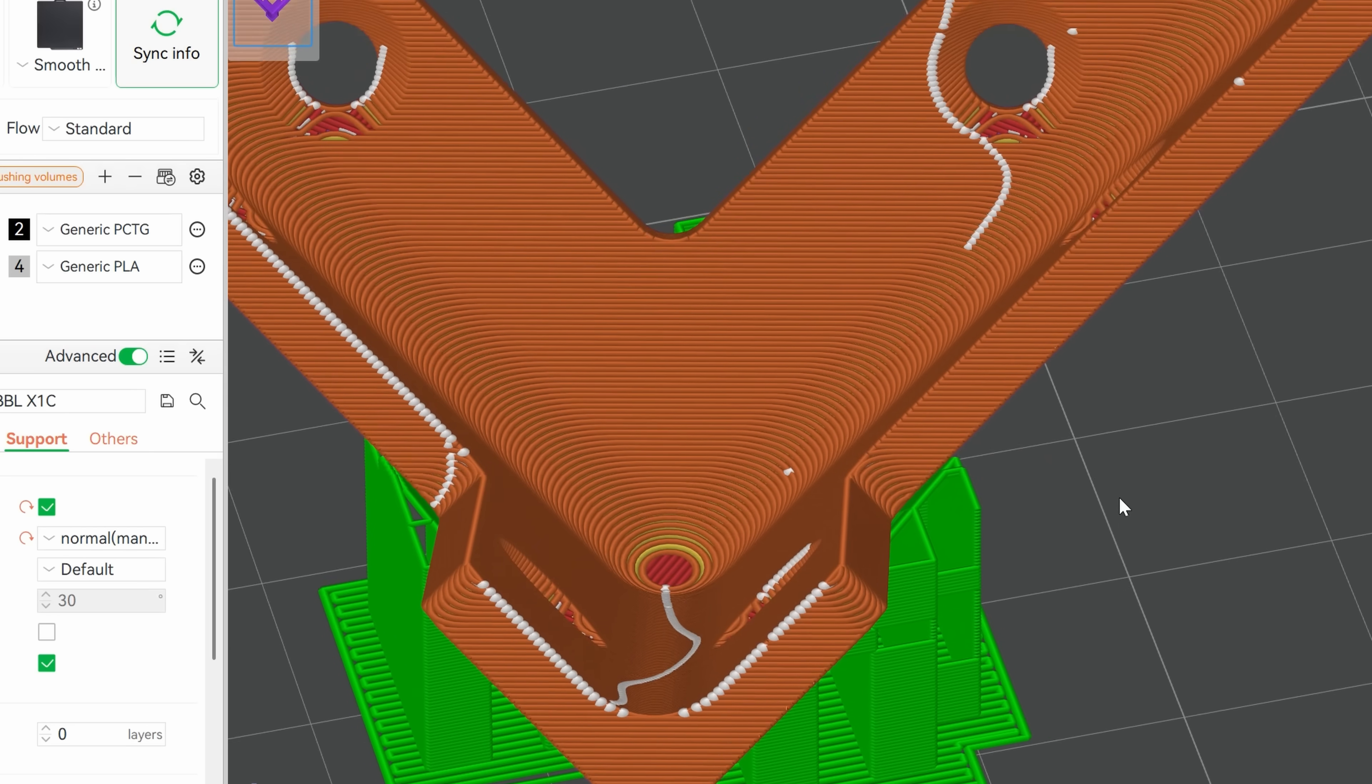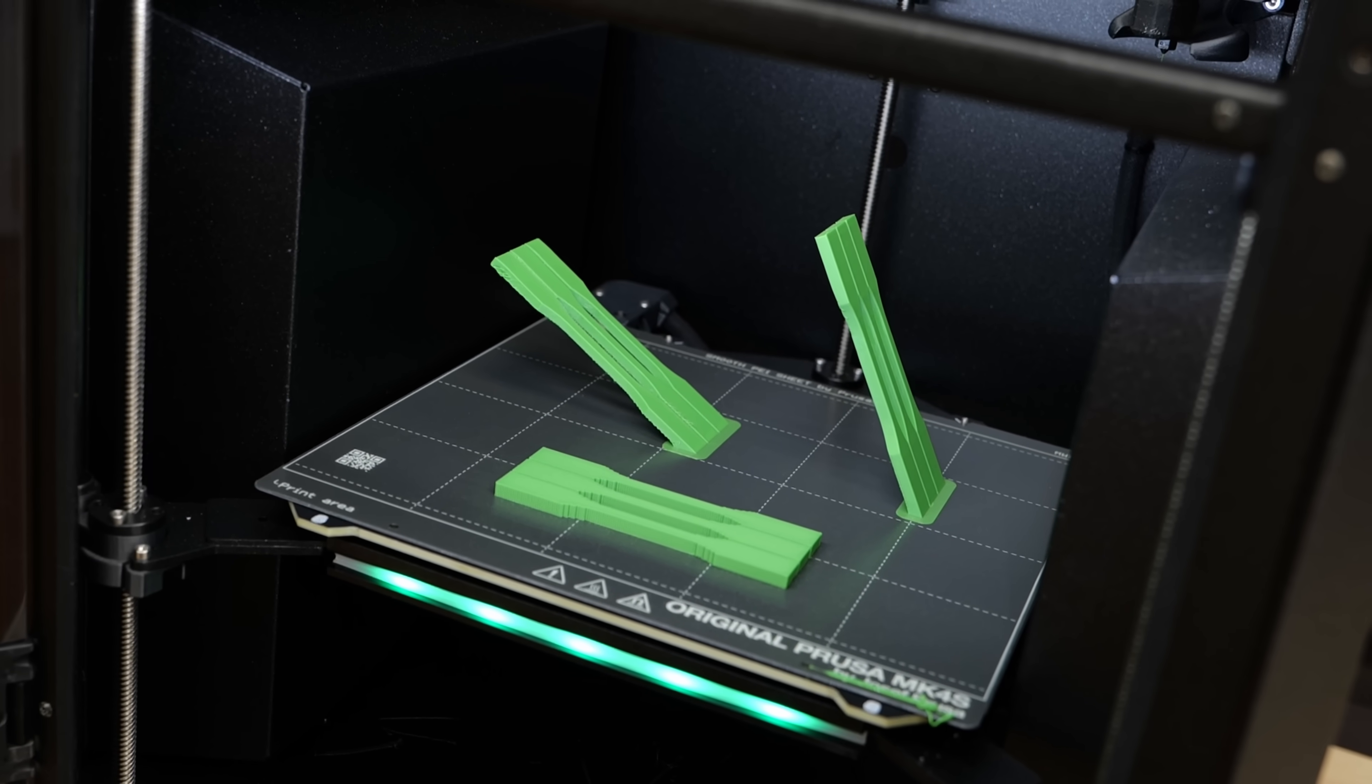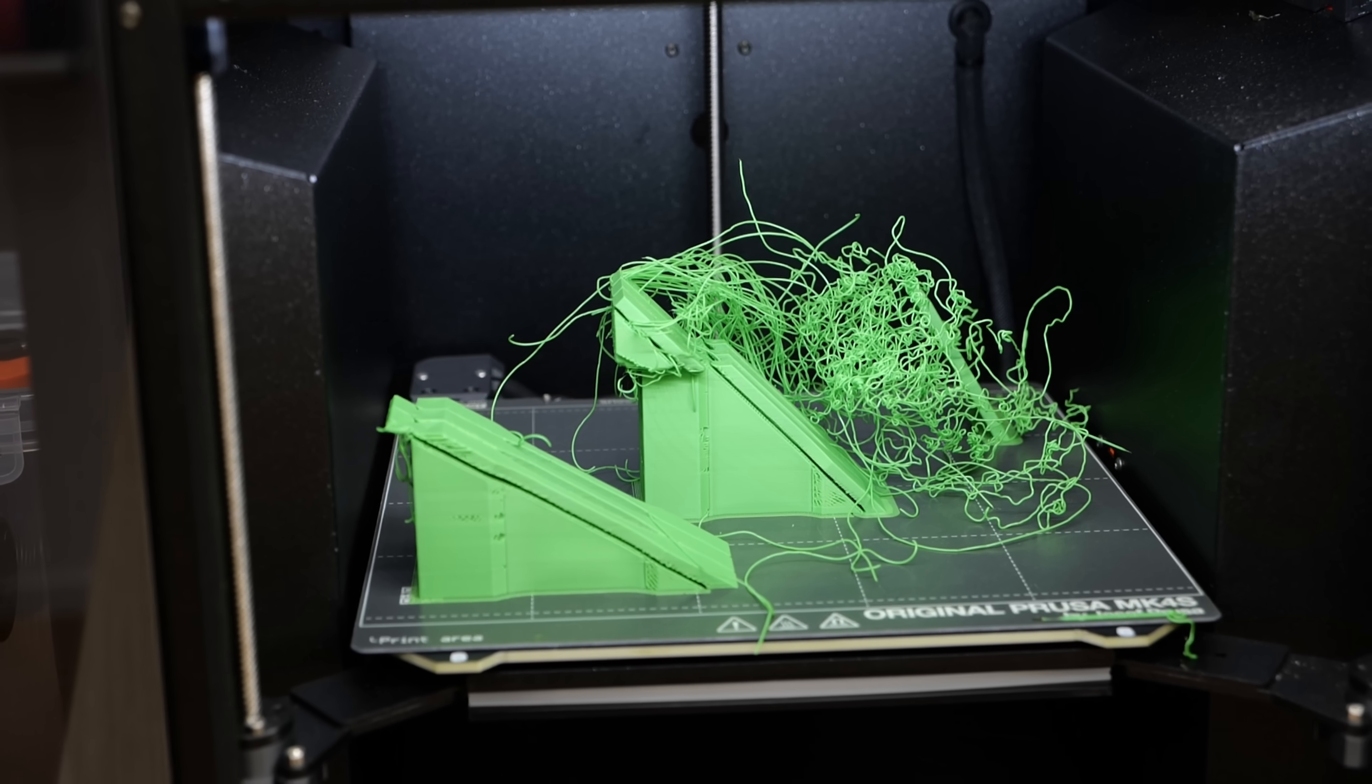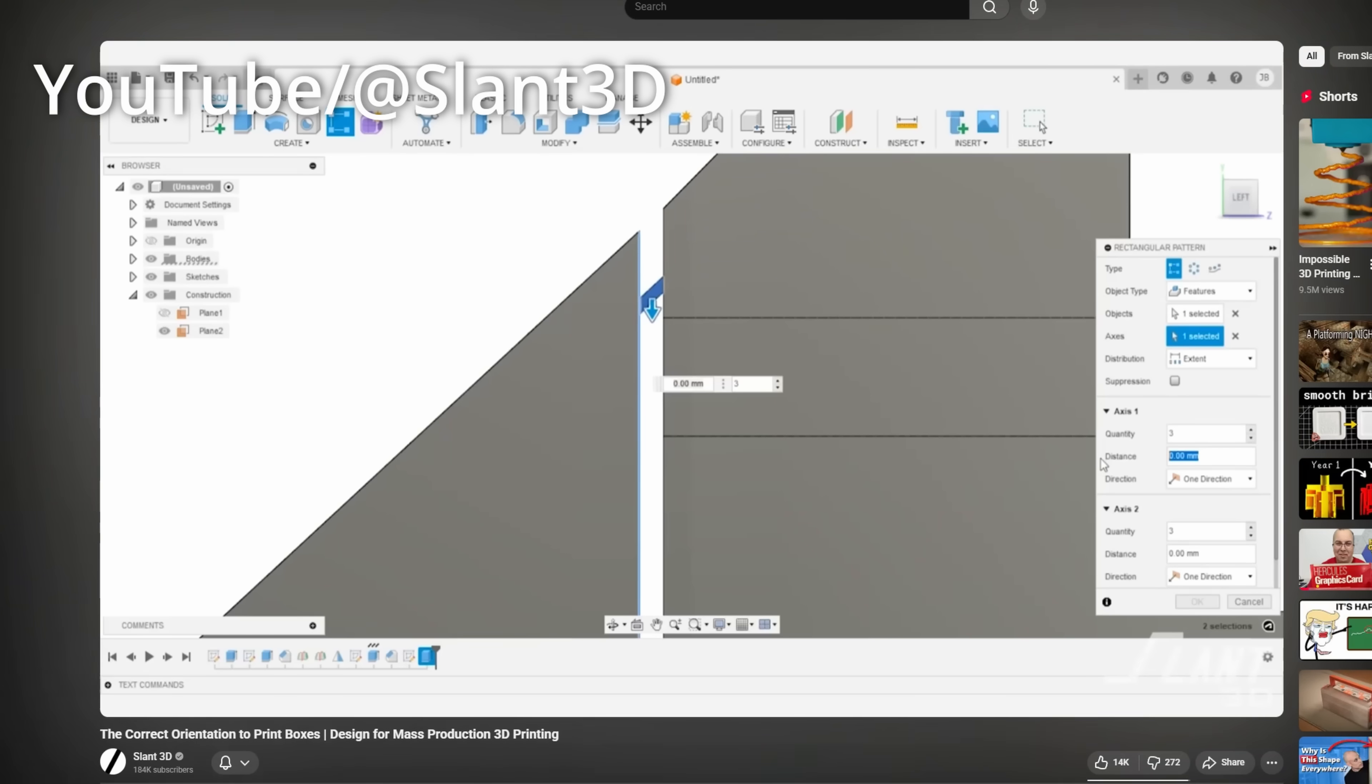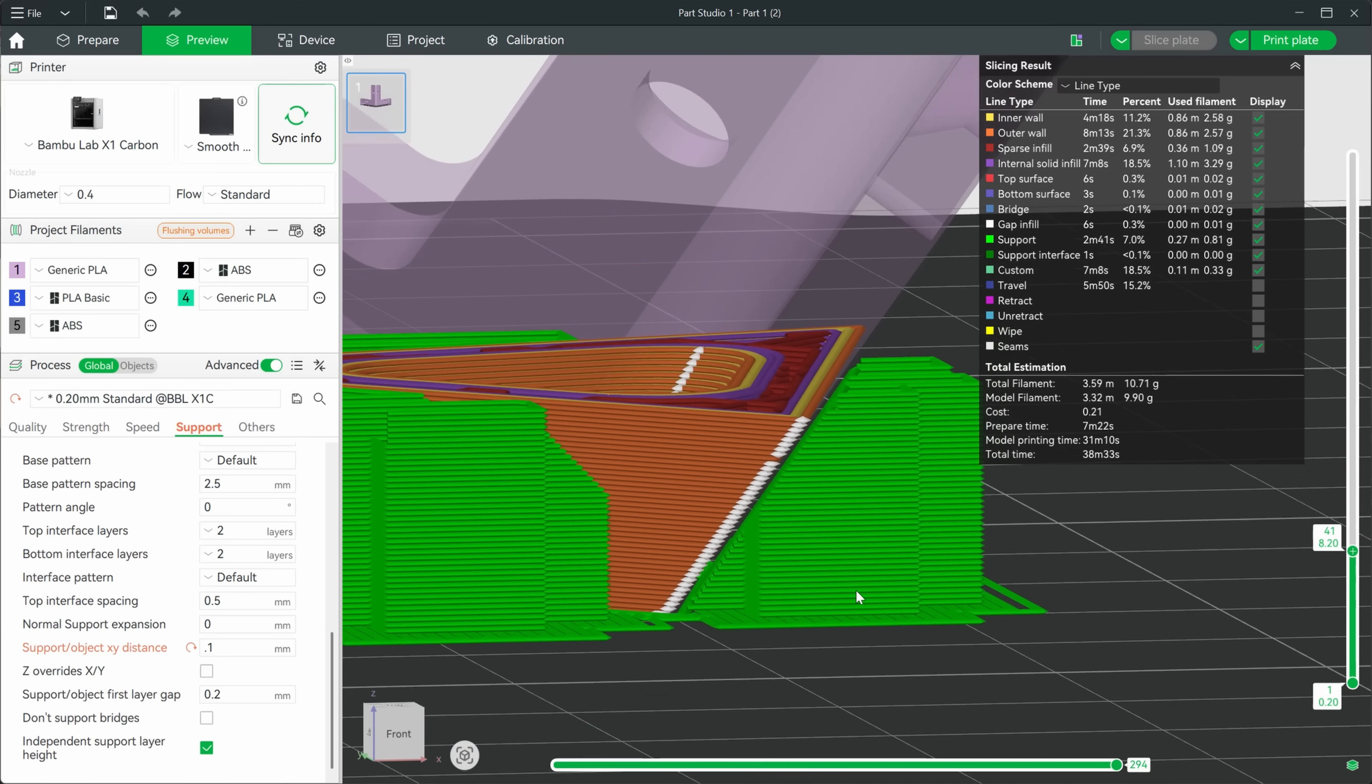But you need to be careful here. I thought I was smart and did exactly that for my angled tensile samples, but all the prints with support failed while the ones without them printed flawlessly. What happened was that even when printing PLA, parts always try to warp and curl up. Initially, the supports prevent this, but since part and support are only loosely connected, I mean you want to separate them easily later, tension accumulates in the part until the support releases. Then the part springs up slightly quickly and the nozzle crashes into it, ruining the print. You can get around this by designing custom supports that are only rigidly connected at a few points and I'll link a video about that from the Slant3D channel below. The dirty way is to just decrease the support/object XY distance in the slicer and live with supports that are harder to remove but hold the part firmly.